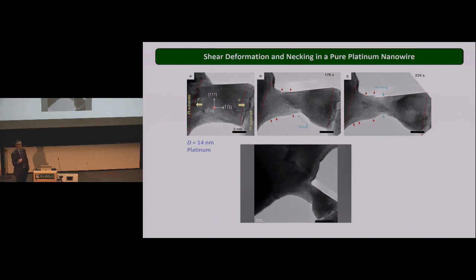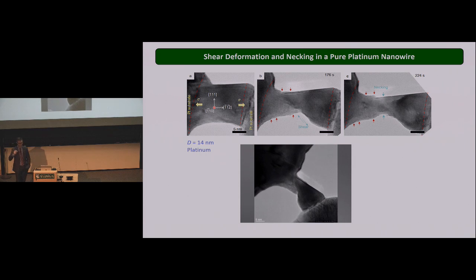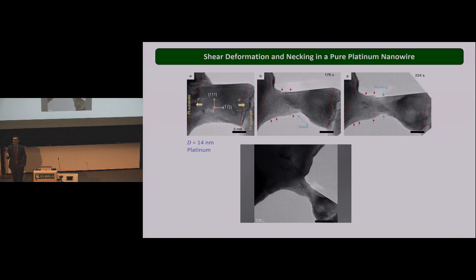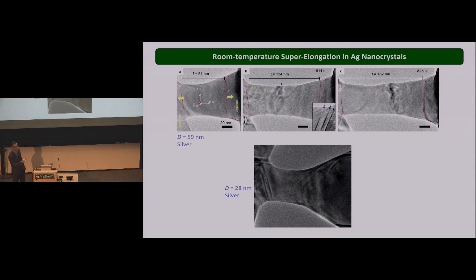So it's a high-resolution TEM video in situ where we pull the crystal. And we see this shear band, which is characteristic of a relatively brittle behavior. So platinum follows what we would expect for gold, for instance. Okay. And now here comes the silver one.